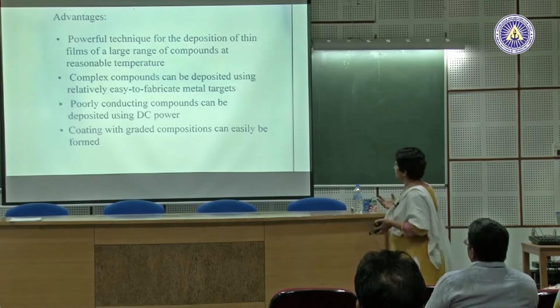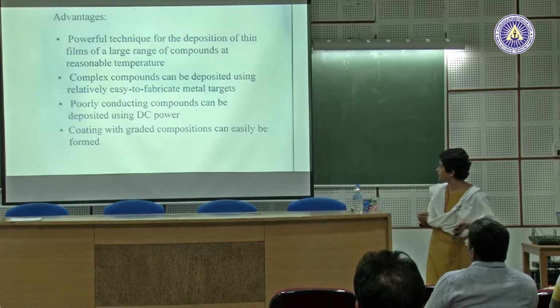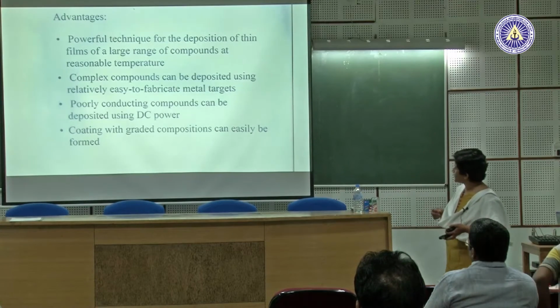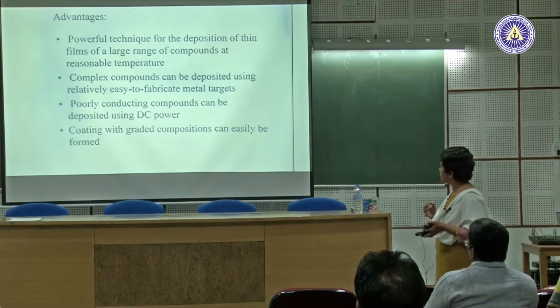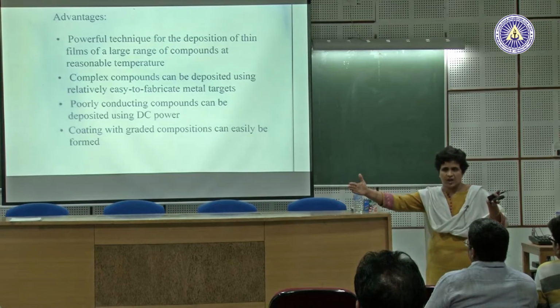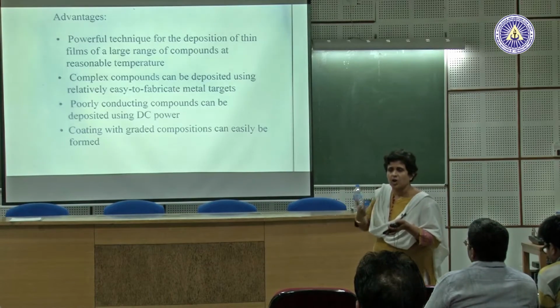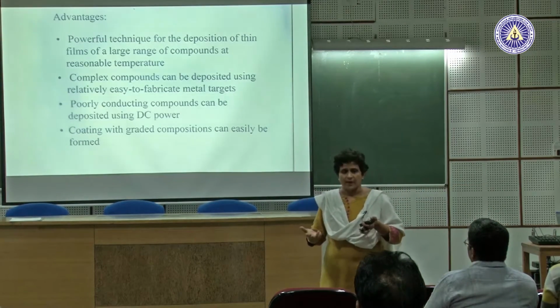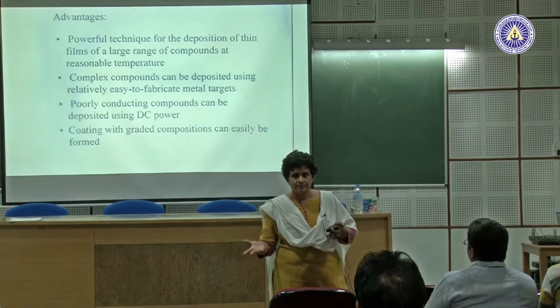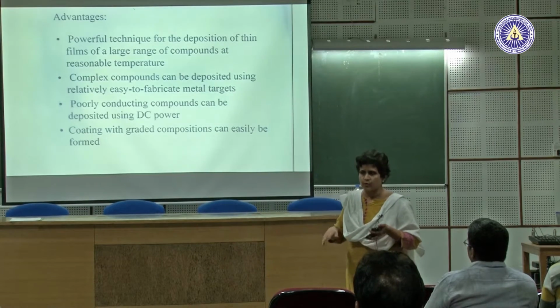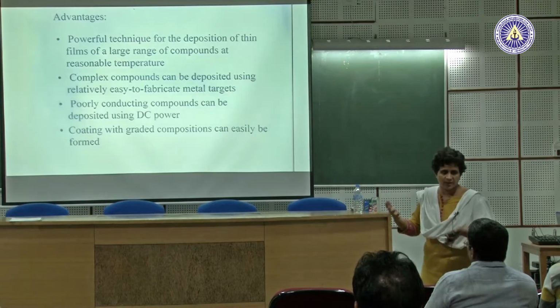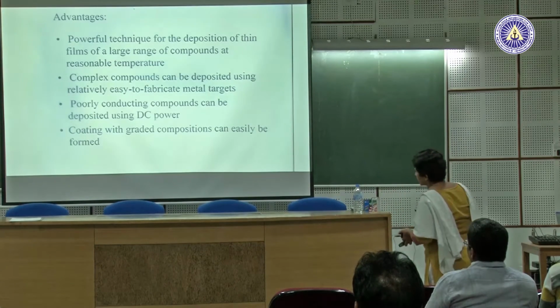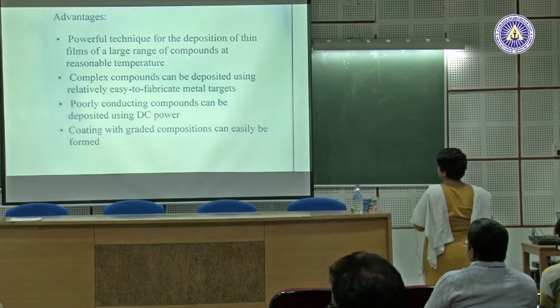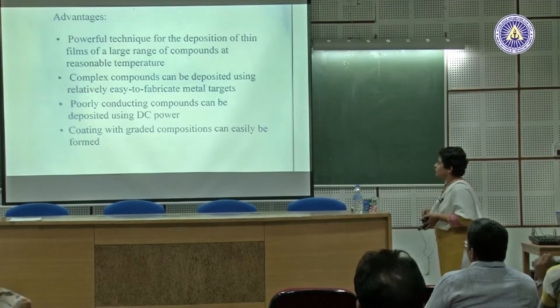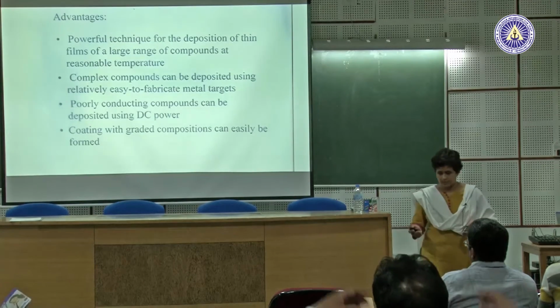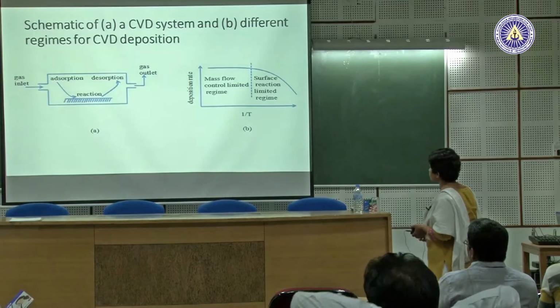Complex compounds can be deposited using relatively easy to fabricate metal targets. There is a little bit of a problem with poorly conducting compounds because it is a discharge. If the target is not conducting, then how do you create the plasma? And the solution is RF. Rather than using a DC supply, you use an RF supply to the plasma, and then you can sustain a plasma even with non-conducting materials. You can create coatings with graded composition, and all those possibilities are there in the case of sputtering.